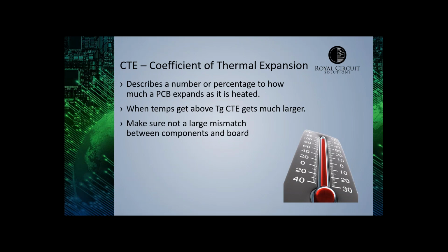All of these then relate to the CTE, the coefficient of thermal expansion. All materials expand as they get heated, whether it's plastic, air, water. The molecules get further apart as the temperature rises. So the coefficient of thermal expansion describes the number or percentage of how much the material expands as it is heated. The glass transition temp is the magic number in this case because below it, it's a linear progression. It expands at the same rate. But once you go over the glass transition temperature, the CTE becomes much larger. So you'll have two coefficients of thermal expansion, one for less than the glass transition temperature and one for more than it.